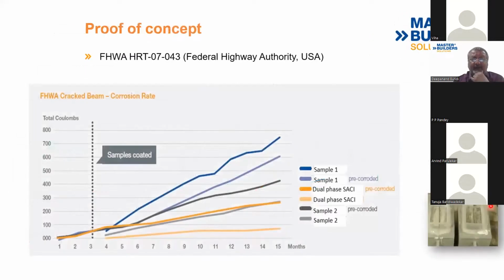With the Federal Highway Authorities, we have checked the samples. The one in blue is sample 1, which is pre-corroded: corroded reinforcement bar, and the coulombs that result, and this is the non-corroded. In gray, you can see a different sample of another company available in the market, and the orange one shows the corrosion levels of the pre-corroded and non-corroded, here and here. So if you have a dual phase corrosion inhibitor applied, after 3 months of corrosion your corrosion initiation is almost parallel to the x-axis, and that's what we need prima facie.